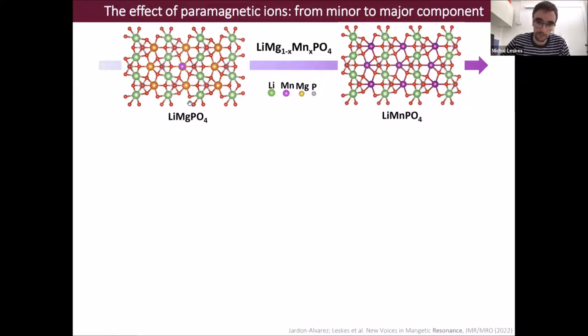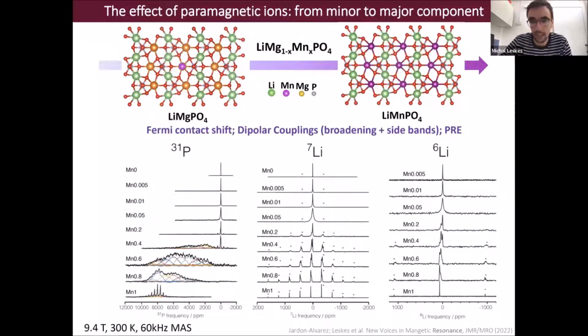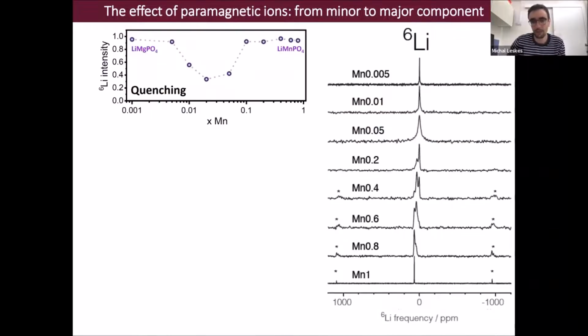And once we had the samples, we did a lot of NMR measurements. And here are shown some spectra. They are very rich in information, because they depend on Fermi contact shifts, dipole couplings, and paramagnetic relaxation enhancement. But today I want to focus on one particular aspect of the spectra, which is the signal quenching and the paramagnetic relaxation enhancement. So let's look at the signal quenching.